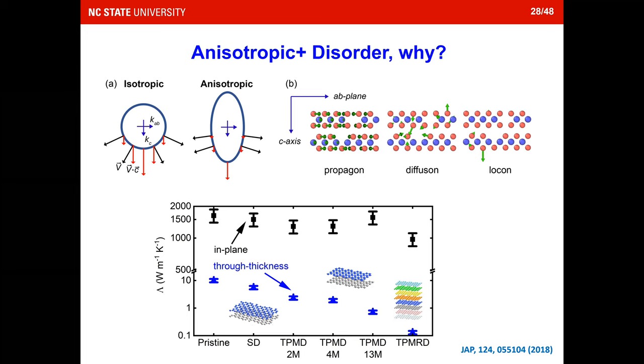But also you need something to break the transportation. If you just have fewer cars passing a bridge, probably that's not extreme. But if you actually put something there to block the cars, then you will completely cut the bridge off. So this is also possible just with disorder, because we later found out there are different modes transporting in solids, and you're able to cut some of the modes using disorder. To test that, we just used simple models first, because directly simulating a complicated model would be time consuming and very difficult. So we asked the student to try a very simple model.